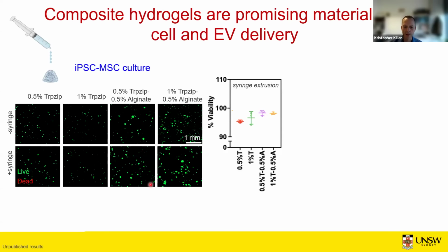And so I think the alginate being bioinert is preventing to some degree the cell's ability to adhere to the nanofibers and spread out and adopt the morphology that we'd seen in previous work. This could be advantageous for some applications. So we'll see. I think we could modify the alginate to make them more bioactive if we wanted to.